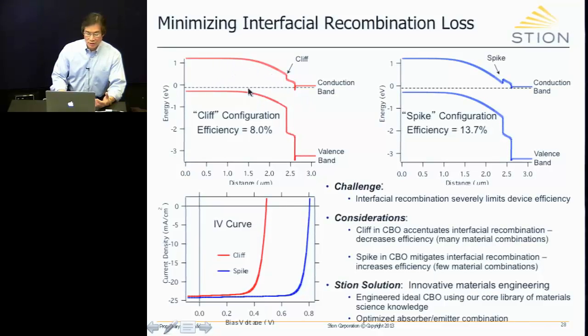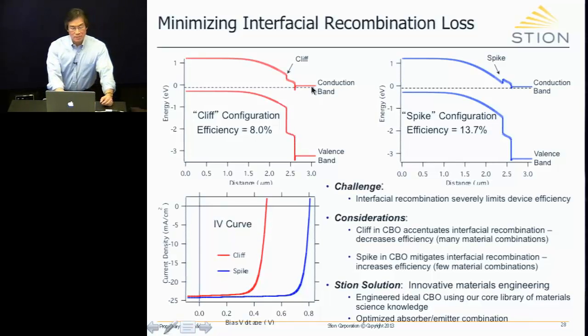You can see that as you get closer to where the heterojunction is, the Fermi level obviously equilibrates there. In this case, you have a cliff because the conduction band offset drops down. In this case, you have a spike because it goes up a little bit. Now, if I asked you which one of these two would be better, don't worry, I won't torture you. You would almost universally say the cliff will be better because the electron can fall downhill and you can collect the carriers better. Well, it turns out that you would be wrong.